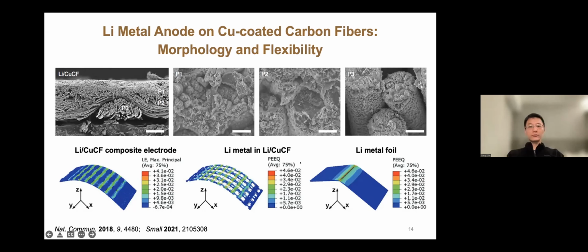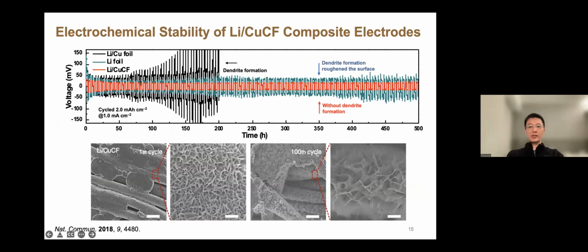So this is mechanically flexible. Electrochemically, it's quite stable. If you see the overpotential, the red curve is our sample that enables long-term stability. And what you see from the electron microscope is that at the very beginning, right over here, about one cycle, you still see a clump or chunk of lithium metal, which most likely we don't like, because that easily initiates some dendrite formation at the beginning.